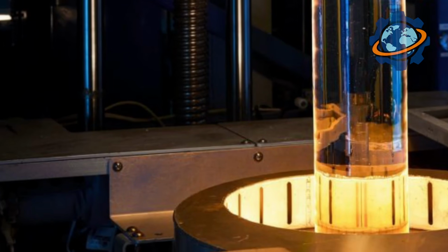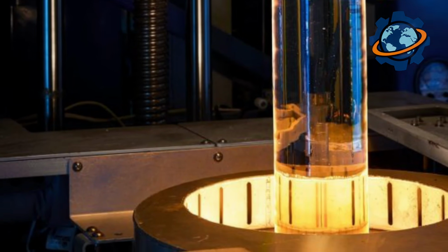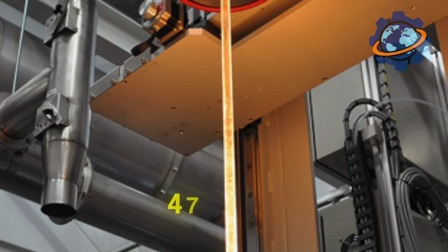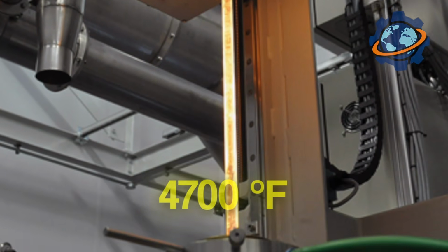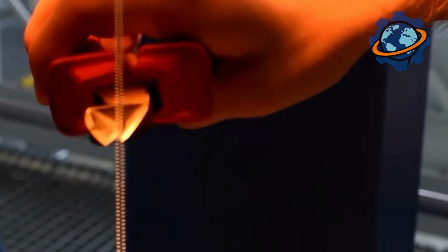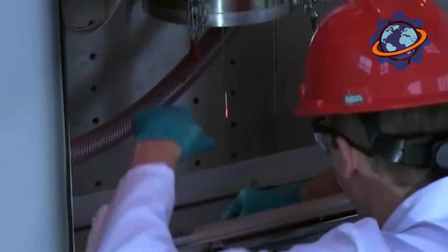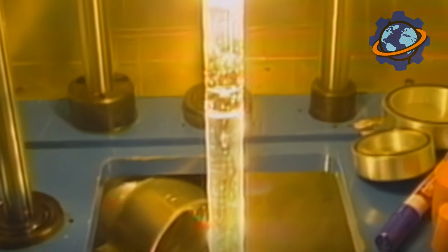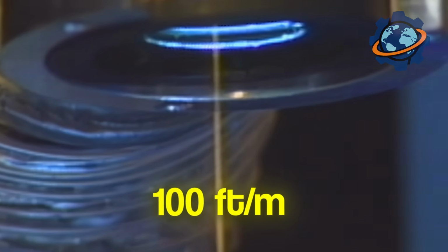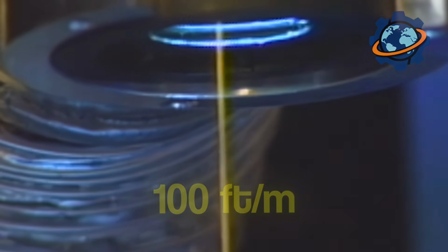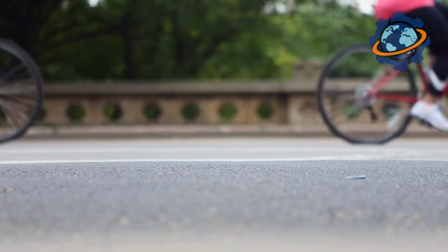The preform is placed in a special furnace that heats up very intensely. The temperature inside it reaches approximately 4,700 degrees Fahrenheit. This temperature is so high that the glass becomes soft and starts to melt, like caramel on a stove. When the end of the preform melts, a drop of molten glass begins to drip from it. This drop is very carefully drawn downwards, and a thin thread is formed from it. This thread, the optical fiber, is drawn at a speed of approximately 100 feet per minute. Imagine that. It's faster than a cyclist moving through the city.